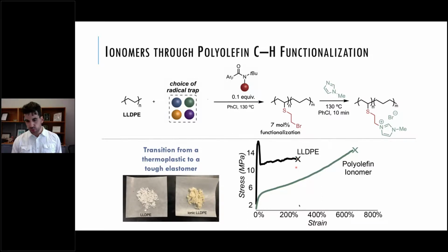You can stretch that about to 3 times its original length before it breaks. By making this ionomer, we make a much tougher material that actually is much more elastic also. So now this has this soft yield point, but now stretches out to about 7 times its original length before it breaks and has this really high toughness. So again, this is some of the things we think we can do, right?